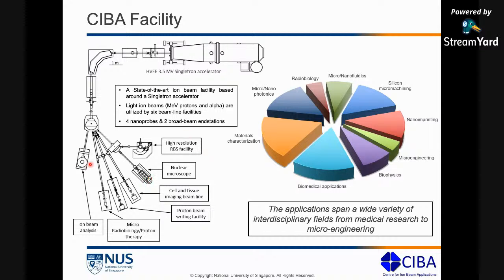One other thing that is different here is that these 4 beamlines, the second, third, fourth, and fifth one, are all focusing beamlines. If you see here, and this will be more evident in the photos I show later on, there are quadrupole magnets on each of these beamlines. What this means is that we can have a broad beam setup where the ion beam is just a broad beam spot, or we can focus this beam using these quadrupole lenses down to a beam spot on the order of 1 micron or even lower, submicron beam spots, and then use this focused beam to scan the sample and then either map an image out of it or collect data out of it.